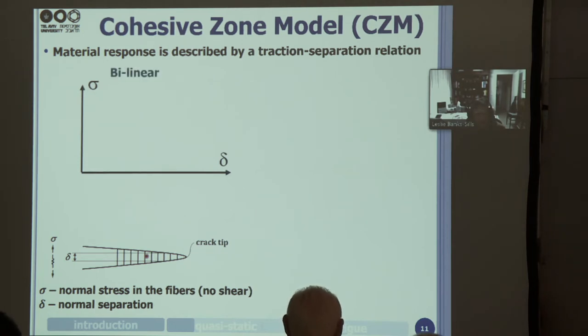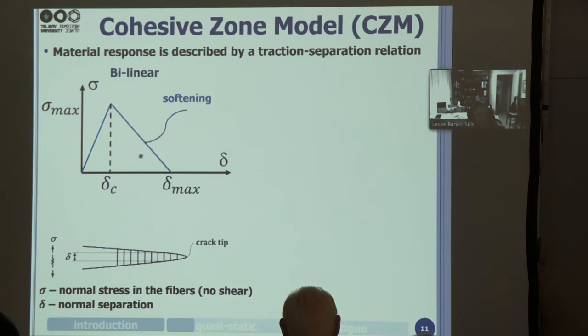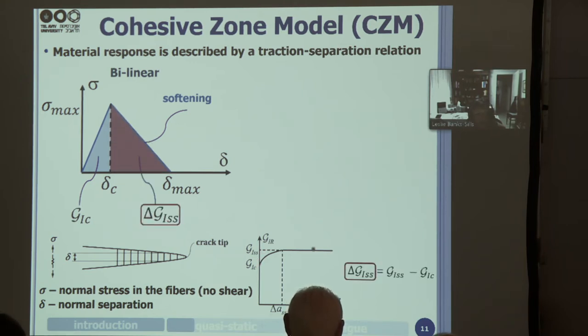So we could have a bilinear traction separation relation where linearly the stress in the fibers goes up linearly to a value of sigma max, and at delta equal to delta C, damage starts and we get softening, and we continue to load and delta reaches delta max, at which the fiber breaks and there's no more stress exerted in the traction separation relation. So under the initial curve, we have G1C, which here's our GR curve, and G1C is the initial critical fracture toughness. And then we have delta G1SS. G1SS is the asymptote that it reaches in the G1R delta A curve, and delta G1SS is the difference between them. So we have the area under the curve.